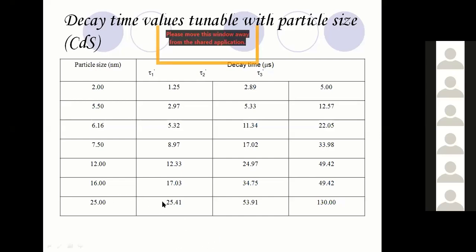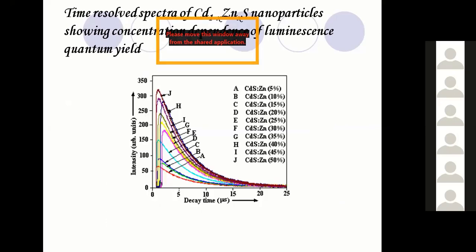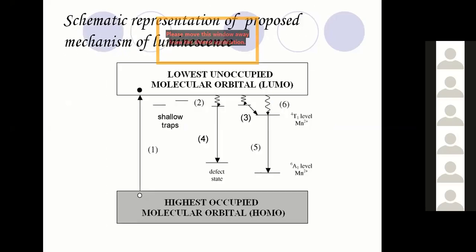In the case of 25 nanometer size particles, the decay time was 25.41 microseconds, but when we go to 2 nanometer size particles, this time becomes only 1.25 microseconds, which is very, very small. So by reducing the particle size on the nanometer scale, we can synthesize fast and efficient phosphor materials for display device applications. These are some other results. We will not be going into detail.